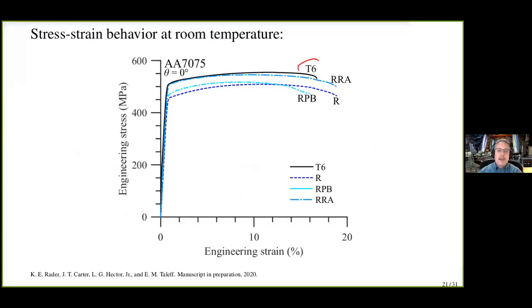Okay, mechanical behavior, simple stress strain curves. Here's our T6 material. Here is our retrogression and re-age material. What we see is we're getting almost identical mechanical behavior. If we retrogress the material, what we find is, boom, we're getting a 10% or so drop in yield strength and in tensile strength. So retrogressing without the re-aging, which is what some of that BMW is doing, seems to just give us a loss of strength. And that's what people have been kind of just tolerating right now. We're getting around that with the re-aging step. Paint bake, and not much improvement in this case. We'll show you a separate case where it gives us a surprisingly better result. Okay, that's kind of where we are in the ballpark, and we're getting elongations of 13, 14% usable in the T6.